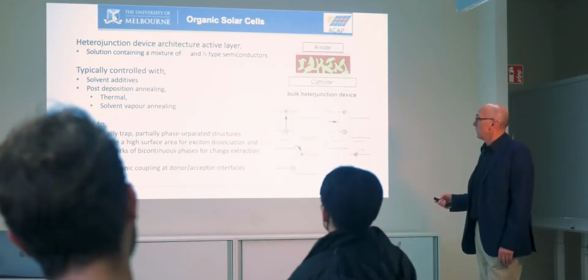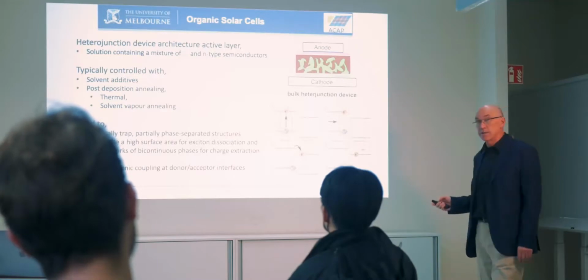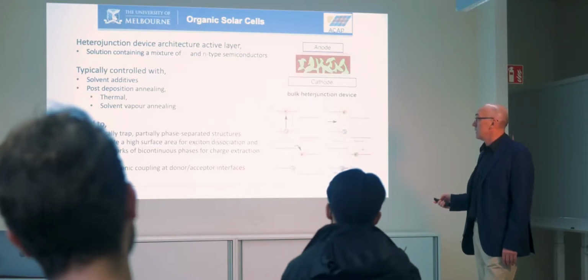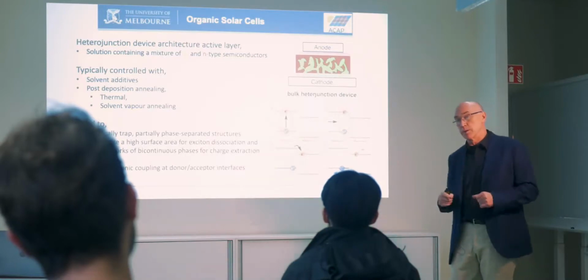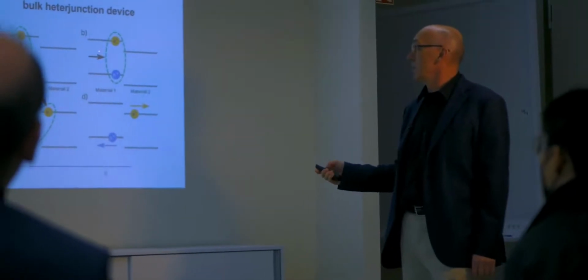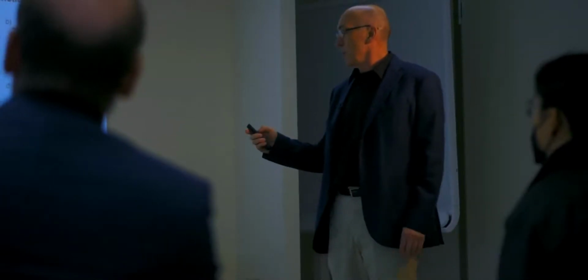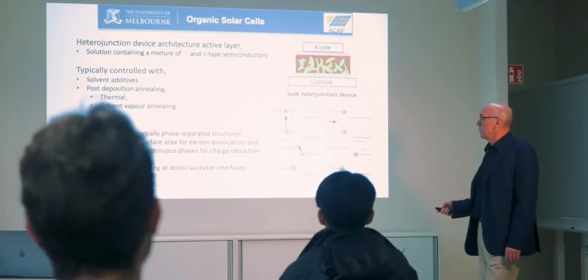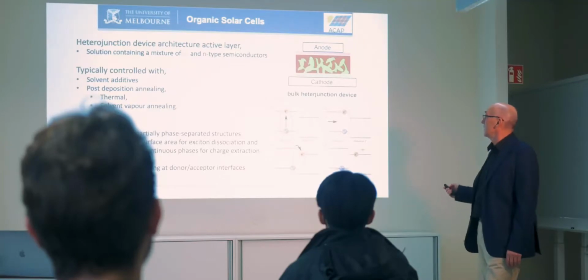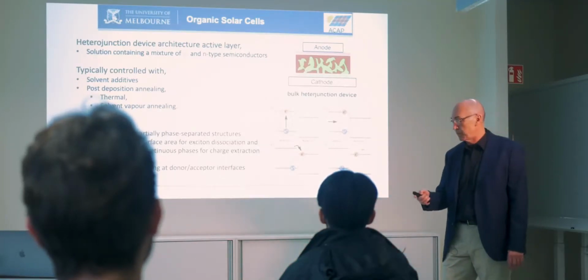Okay, so another couple of things we're looking at, of course, is we want to tune the electronics at this interface. Very quickly going through how these solar cells work. We absorb light and we generate an excited state. This is an exciton, a coulombically bound electron-hole pair. And therefore this diffuses to an interface. And because this has a binding energy, it takes energy to break it apart, we need an offset between the P-type material and the N-type material, the donor and the acceptor. And so this is where we get separation of charges. Okay, there's a lot of work now going on to say that we can reduce this offset, but let's say that it needs to be an offset there. So we need two materials. And so we can tune the electronic coupling at this interface in this bulk heterojunction by deposition, by post-deposition treatment.